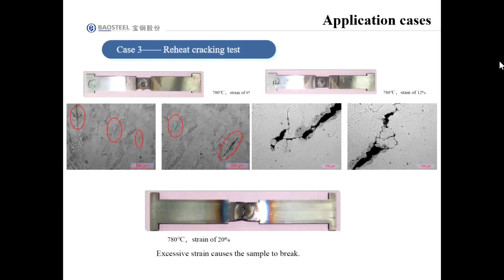This is the metallographic observation of the welding zone at the temperature of 780 centigrade with different strains, from 0%, 12% and 20% of the strain respectively. In the end, the largest strain, for example the strain of 20%, causes the sample to break. So this is all about part C.